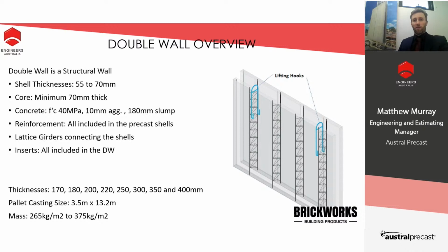So double wall is a structural wall. The main thing for double wall is that the shell thickness is critical to the overall structure and the temporary works of the product. Shell thicknesses can be made from 55 to 70 mm, with 70 mm being the standard size of our formwork in our factory. The core of double wall requires a minimum thickness of 70 mm, and this is so that we can get the starter bars and any joint reinforcement into that core prior to concreting on site.